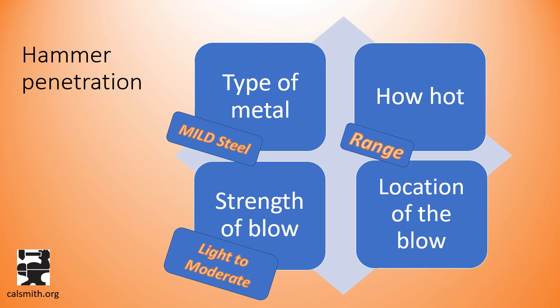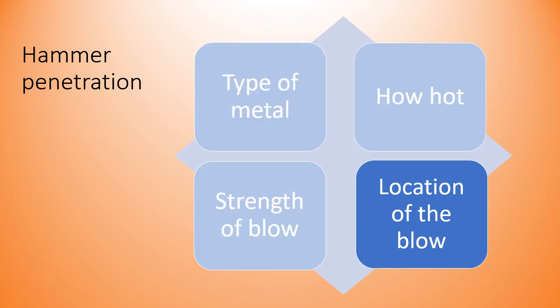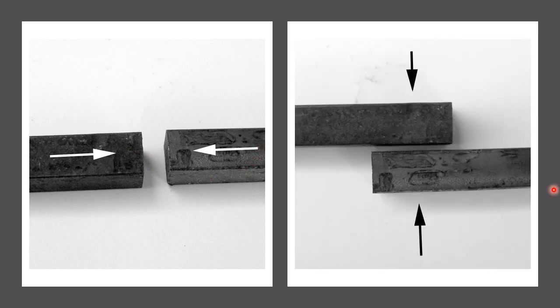And finally, we get to the location of the blow. The location of the blow is going to lead us into a discussion about why we form a scarf. If you wanted to weld these two bars together, you would need to hit them from the side. If you had two bars positioned one over the other, like this setup for a lap weld, you'd want to hit them from this direction or this direction in order to weld here.